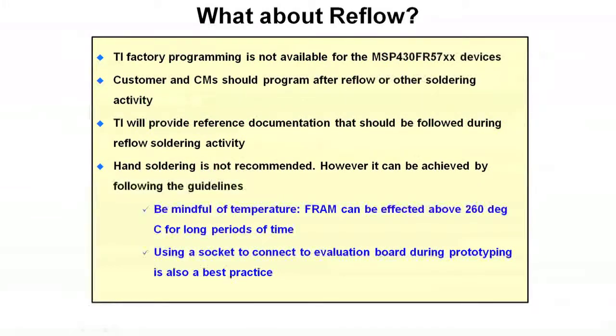FRAM devices are somewhat susceptible to higher temperatures. TI factory programming is not available for FRAM devices — you should program the devices after reflow or any other soldering activity. Reference documentation should be followed for reflow soldering. Hand soldering is not recommended because you can concentrate so much heat on the part, but it can be done by following guidelines: be mindful of temperature, as FRAM can be affected above 260 degrees C for long periods. Using a socket on an evaluation board during prototyping is also a best practice.